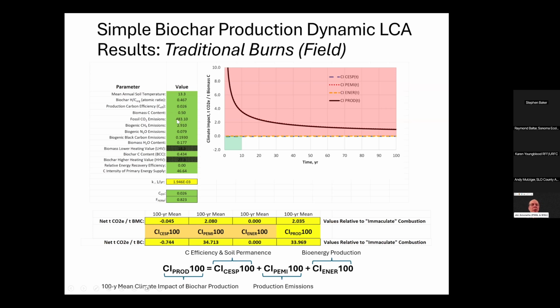This number I just want to mention, this is the CO2 emissions generated primarily by use of the excavator to load and move biochar and move biomass around at the Usal site. When you add this up, it does have an impact overall, but it's just something we need to consider whenever we're doing this work, in that particularly diesel has a very high black carbon emission, depending on whether you have a filter or not on your system. That's a bad way to generate more emissions than you really want in your overall footprint. So run the cleanest diesel equipment you can is the message.